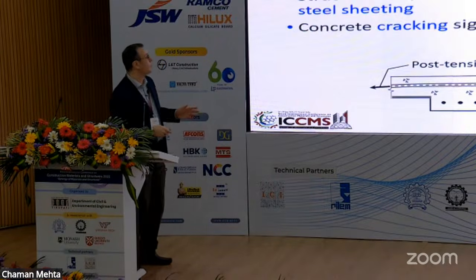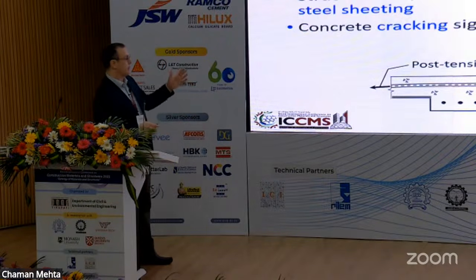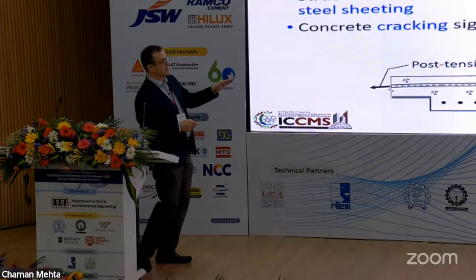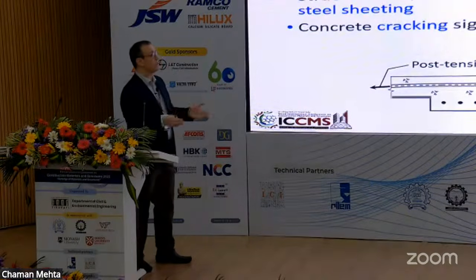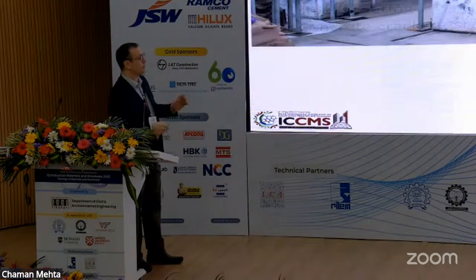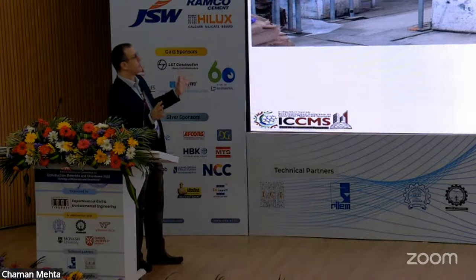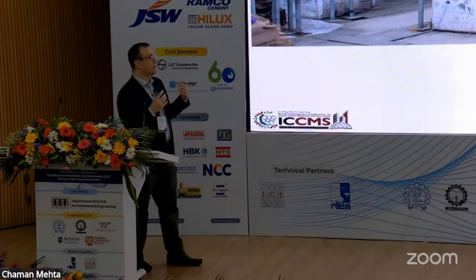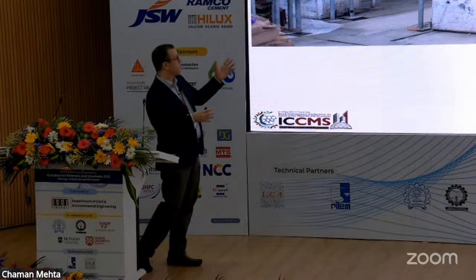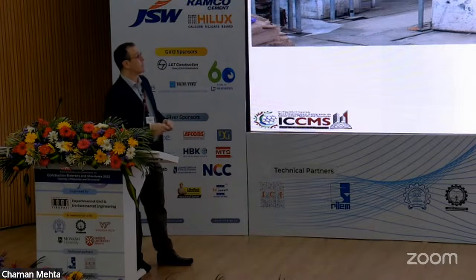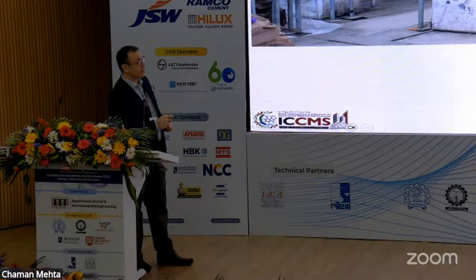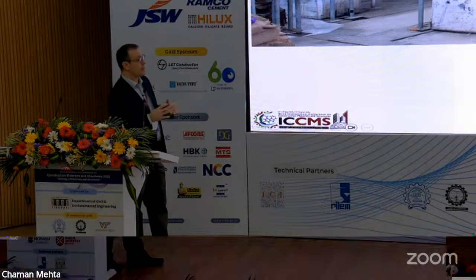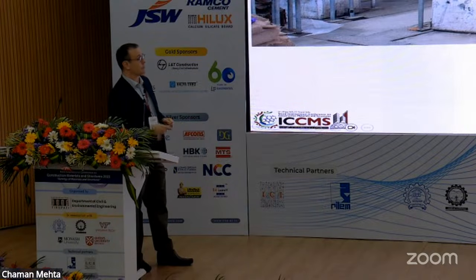And we've been involved in a project where we've been asked by a number of companies, Art was involved in that, to look at this and say, can we take advantage of the composite steel sheeting? When we start a project like this, we usually start with some tests that demonstrate to us what is happening. So we had a lot of samples of this type where we tested simply supported post-tension slabs, and we did some unreinforced concrete measurements just to measure the shrinkage behavior.